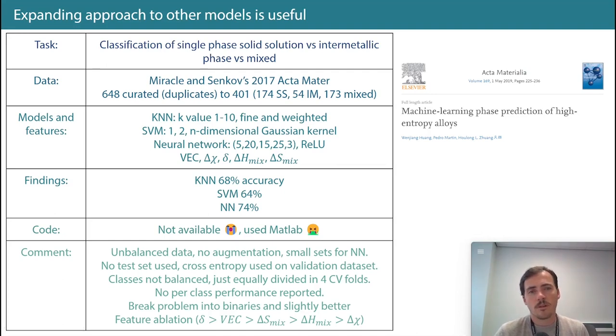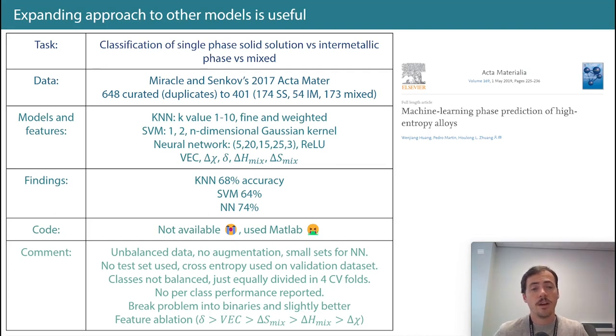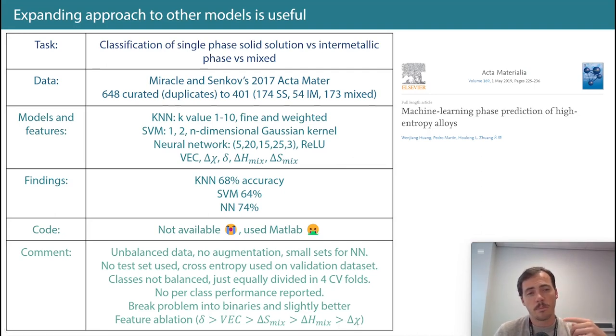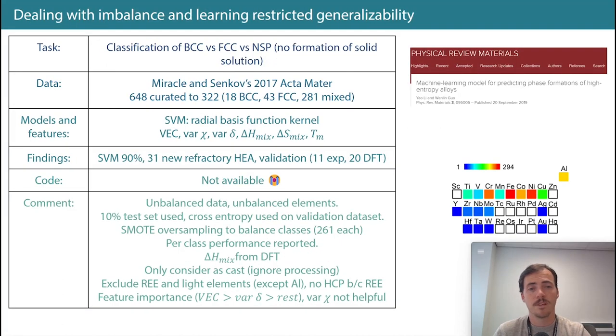They did report feature ablation to get feature weights for those five features, and found that atomic radii difference was most important, followed by valence electron count, followed by entropy of mixing, then enthalpy of mixing, then electronegativity difference. You'll notice that more papers are doing feature weighting, and they don't always get the same trends — they vary significantly.